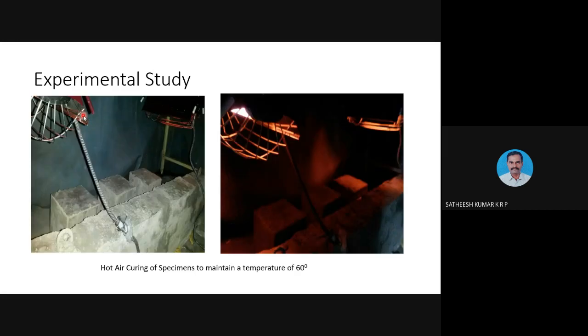This was the arrangement which we used to cure the specimens. What you can see here at the top is a room heater, because we don't have a facility to cure beam specimens. In our institute, we have a hot air oven, but the capacity of the hot air oven is not sufficient to cure beam specimens. So what we did is we used a thermal enclosure, and within this thermal enclosure we had room heaters, and these room heaters were further controlled using voltage stabilizers and voltage regulators. In that way, we were able to control the ambient temperature within this enclosure. We were able to maintain temperatures of around 60 to 80 degrees Celsius for 24 hours.